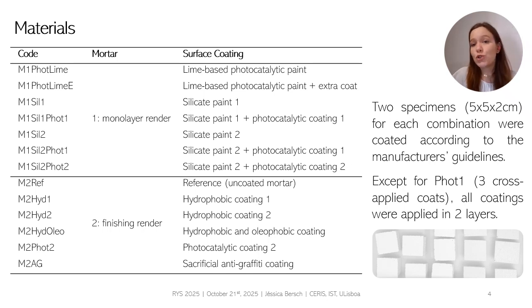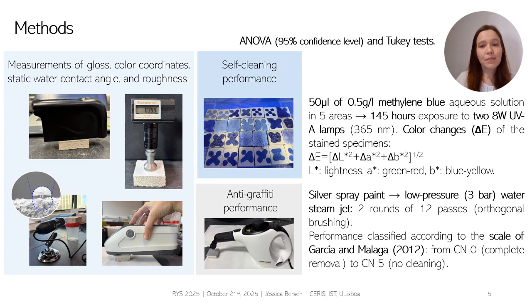Mortar 2 is a two-layer system, and the outermost layer was considered as a finishing render. That is why it was studied uncoated as a reference, and with the application of two different types of hydrophobic coatings, a hydrophobic and oleophobic coating, with photocatalytic coating 2, and with a sacrificial anti-graffiti coating. Two specimens were tested for each combination and were coated according to the manufacturer's guidelines, normally with the coatings applied in two layers.